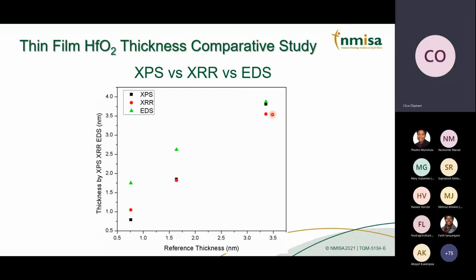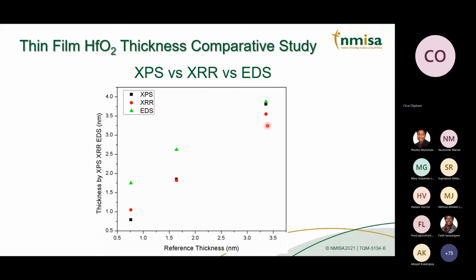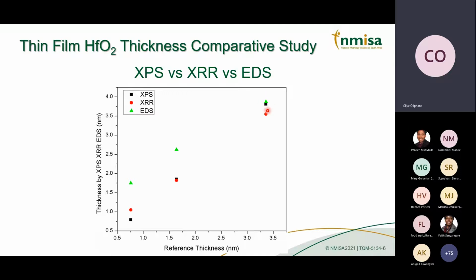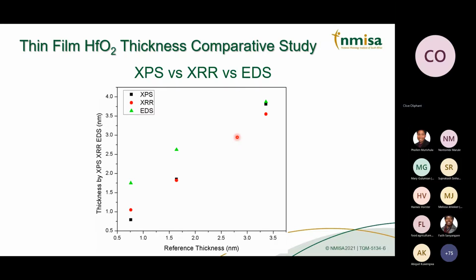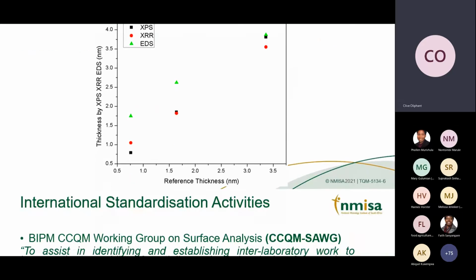At slightly thicker thicknesses of thin film, the EDS and XPS can compare. However, the XRR is slightly dependent on the density. This graph just shows us that there are differences, and even though you can measure the film thickness, comparing it, we need to be aware of the limitations of techniques as well. EDS for very thin films can become quite inaccurate. However, XRR and XPS can still be highly comparable. So there are different ways for measuring different things. We just need to be aware of the limitations of each technique to ensure that we measure these materials correctly.